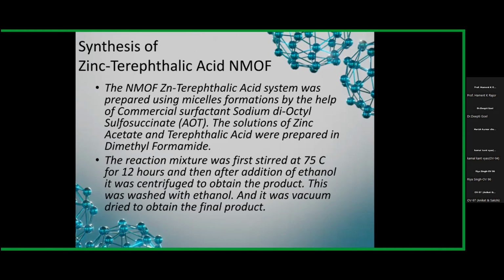First, the NMOF zinc terephthalic acid system was prepared using micelles formation by the help of commercial surfactant sodium dioctyl sulfosuccinate, which is also called AOT. The solutions of zinc acetate and terephthalic acid were prepared in dimethyl formamide. Second, the reaction mixture was first stirred at 75 degrees Celsius for 12 hours, and then after addition of ethanol, it was centrifuged to obtain the product. This was washed with ethanol and it was vacuum dried to obtain the final product.